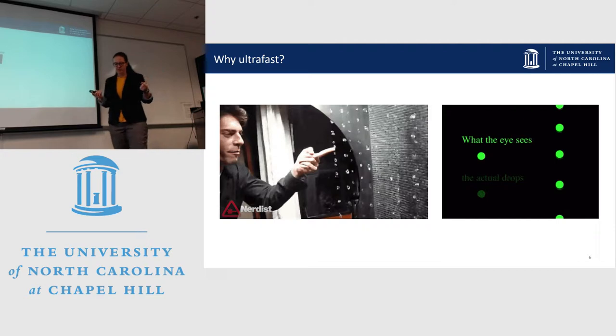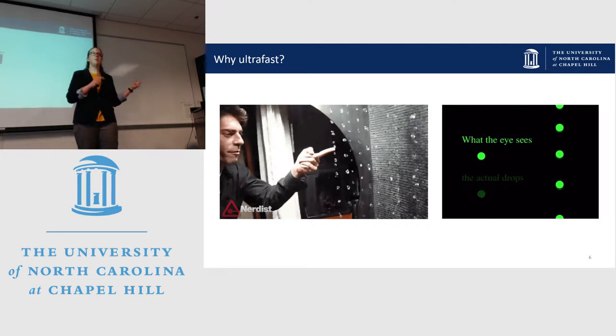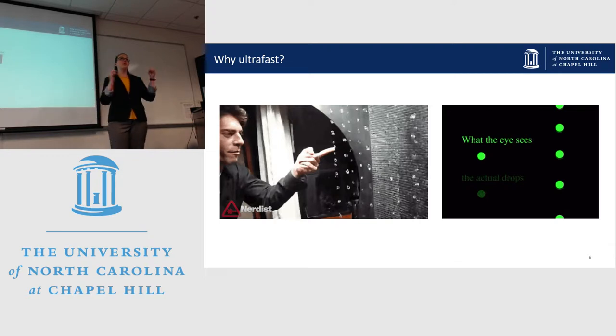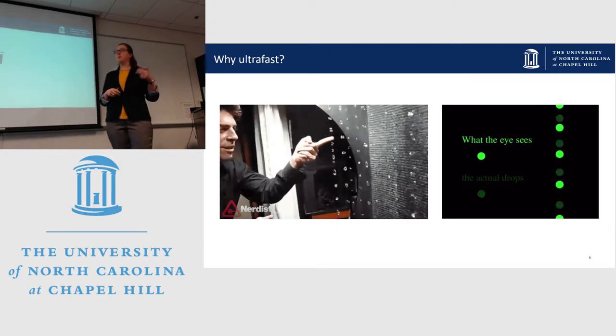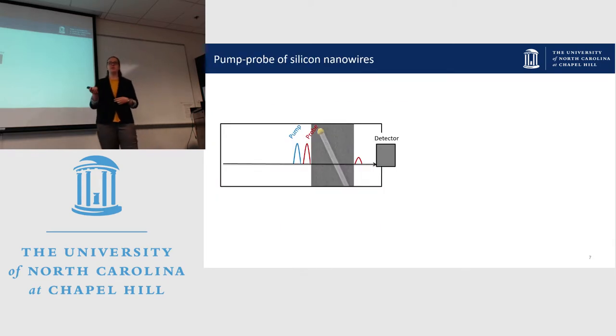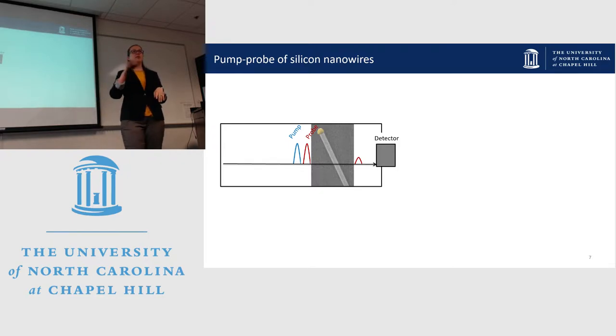So we do something very similar, except, again, we're looking at things that happen in hundreds of femtoseconds. Instead of a flash bulb, we use laser pulses. Specifically, we use two. The first is 425 nanometers, or blue light, and it excites a bunch of carriers in our nanostructure, electrons and holes. That's the equivalent in our analogy of releasing the droplet of water. We then use a second pulse, which is red light, or 850 nanometers, and that acts like our flash bulb. In silicon, when you excite carriers, the silicon becomes more transparent to that second flash pulse, or our probe.